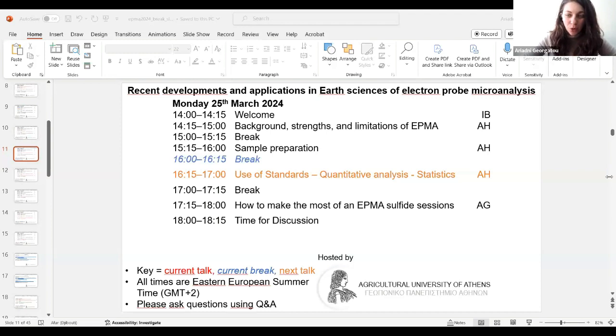Will polishing with lower abrasive size, less than 1 micron, be beneficial or increase the counts for trace element and light element analysis? For light elements, absolutely. Again, the problem with light element analysis is that they are all low energy X-ray lines. Low energy X-ray lines are also L and M lines of other elements. So it doesn't always have to be strictly oxygen or nitrogen. It can also be that you have to analyze the gold M line, which gives you the best peak to background. And those are very susceptible to topography because the amount of absorption changes. And so the better the polish for these kinds of materials, the better is your data.